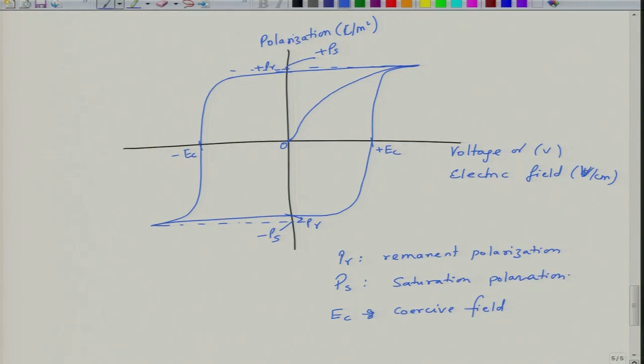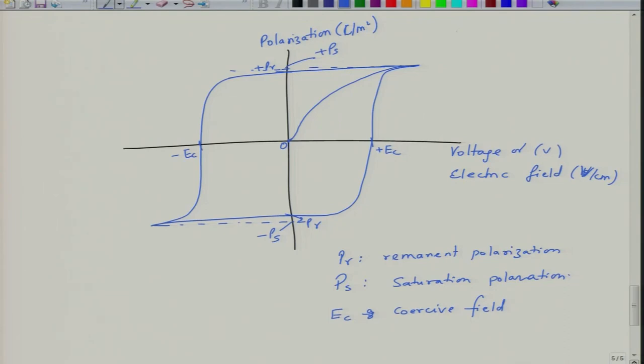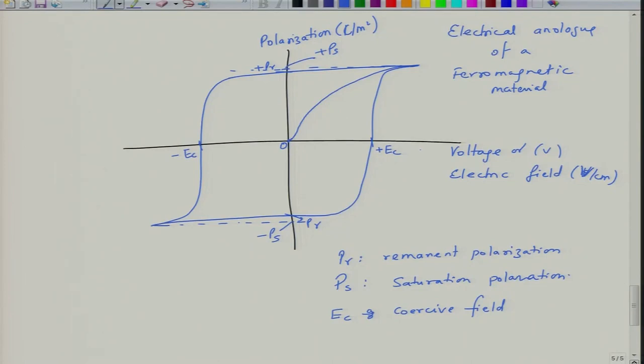This is basically because of, as we will see later on, formation of domains in these materials. The switching process is somewhat similar to what we see in ferromagnetic materials. So in some sense you can call it an electrical analog of a ferromagnet. In a ferromagnetic material, this loop exists between magnetic field and induced moment or flux density, whereas in this case, this is a loop between voltage or electric field versus polarization. Polarization is charge density, and this is the electric field. So you are measuring the charge density on a capacitor, and this is what you see.